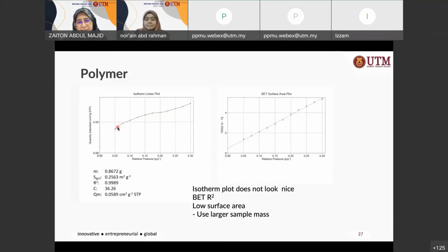If you notice, the isotherm increases, decreases a bit, and increases a bit, right? As we have seen earlier, if you increase pressure, the volume uptake should increase. Remember, when we look at our earlier schematic diagram, at P1 you have adsorption of gas molecules. And then as you go to increasing pressure P2, whereby P2 is greater than P1, you should have more gas molecules adsorbed. But if you look at this isotherm, there is a decrease between maybe 0.18 to 0.2 and then an increment. Something doesn't look nice here, right?